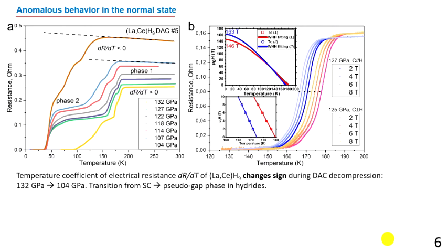Okay, let me show another example we recently discovered. Together with my colleagues from Jilin University, we investigated the lanthanum cerium H9 ternary hydride. In one cell it demonstrates, as usual, superconducting transitions. In one of the cells we found that during decompression, temperature coefficient of electrical resistance also changes its sign. At high pressure the sign is positive, but at low pressure during decompression it changes the sign and the sign is negative. So resistance decreases as in semiconductors when the temperature rises, and the dependencies are almost linear.